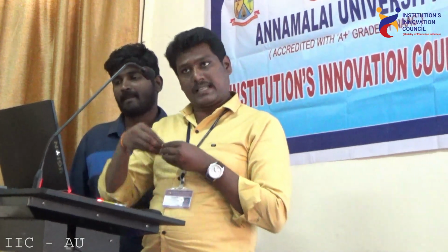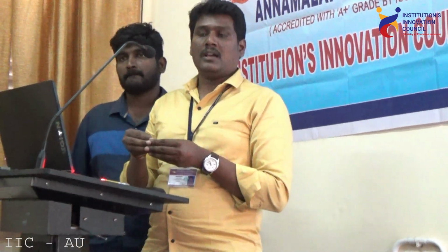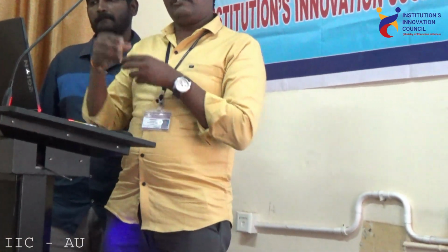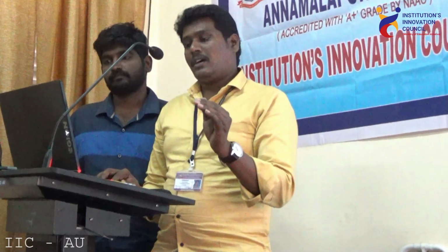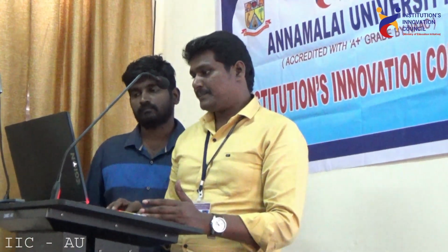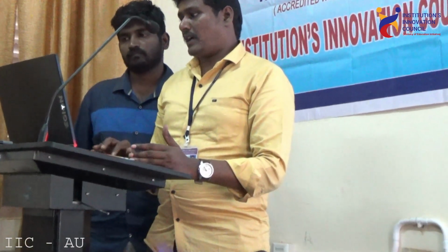As I said before, the magnesium will segregate and it will form precipitate. Actually magnesium is a solid solution strengthening alloying element. When it is completely dissolved in the aluminum matrix, it will provide strength. But if it takes more time to segregate, then it will form precipitate. So in both components, CMT and GMAW, the CMT component has a lower mass percentage of magnesium in the precipitate, which means more magnesium has completely dissolved into the aluminum matrix. That is also the reason for the higher strength in the component. This is for the bottom region. In the top region also, the CMT components have less volume of magnesium precipitate.